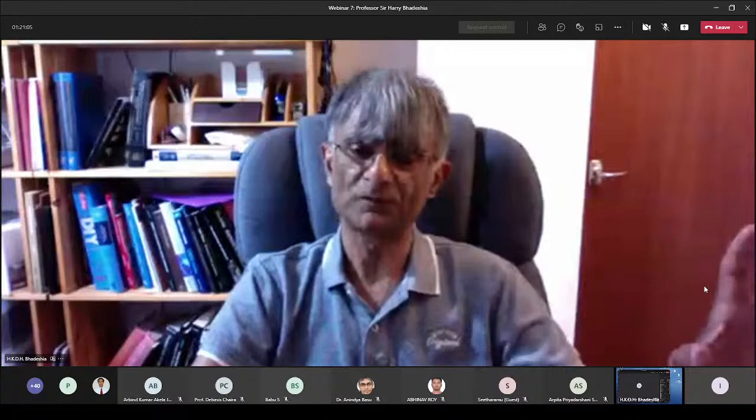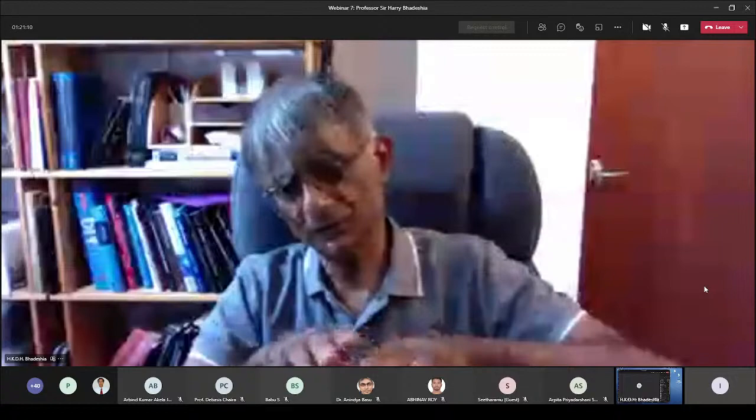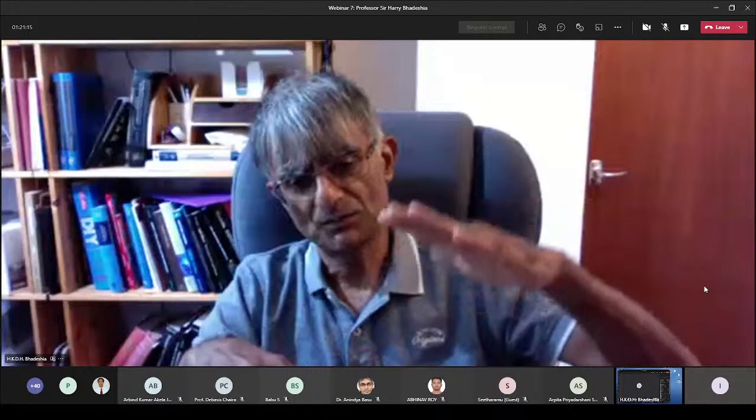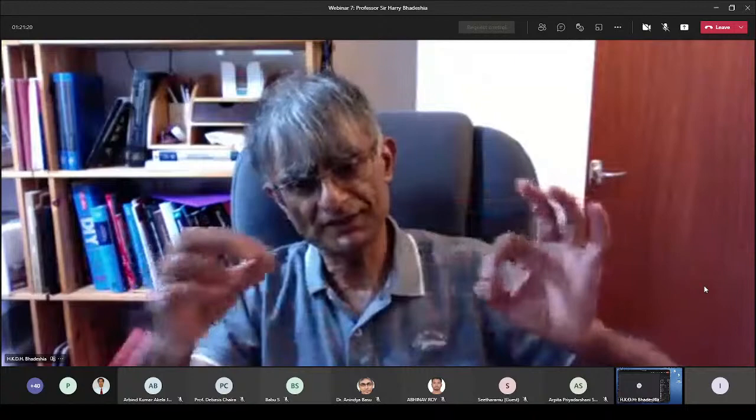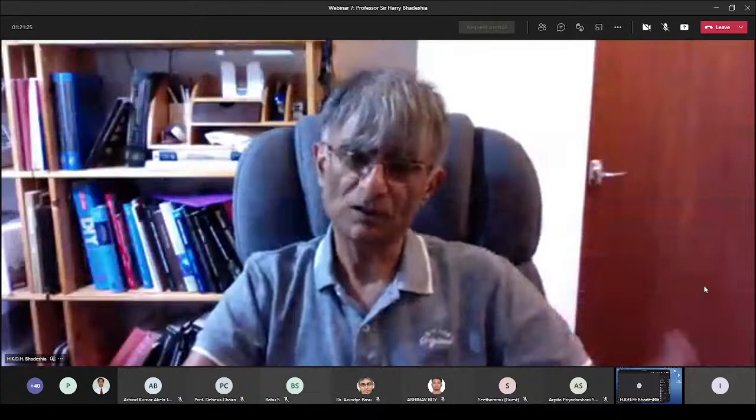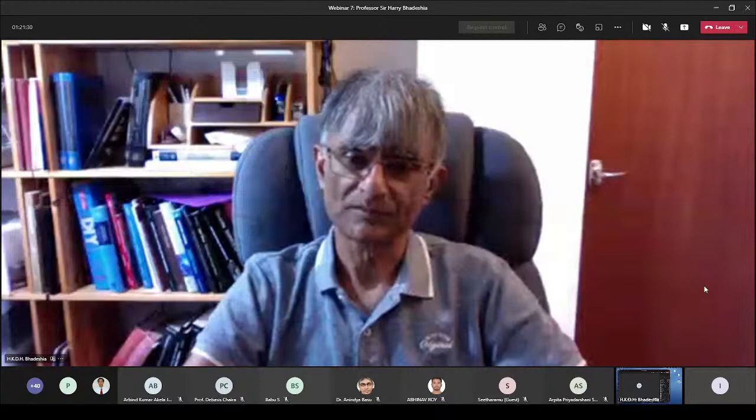But by the time you come to observe it, many of these plates, because of the low carbon concentration, are touching and the morphology looks a little bit confused. But if you stopped the transformation at an early stage, you would see exactly those plates of bainite that I was showing you. So acicular ferrite in low carbon steels is the same as bainite. Okay, thank you.